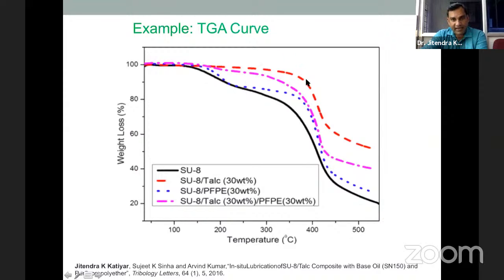In this graph, in red color, you see only one decrement. After this, the decrement starts. But in the bluish color, up to 100 degrees centigrade, whatever moisture is present is only evaporated, so that loss in the material is due to moisture. But after 100 degrees centigrade, why the mass loss or weight loss happens is very important. The bluish color shows a primary decrement and a secondary decrement.